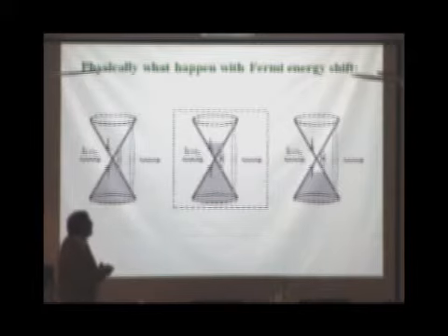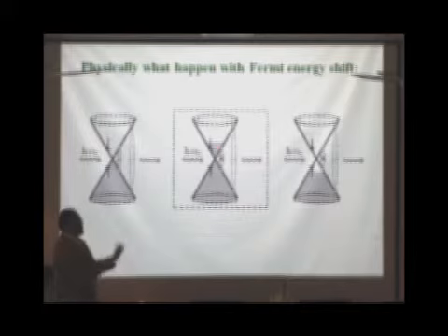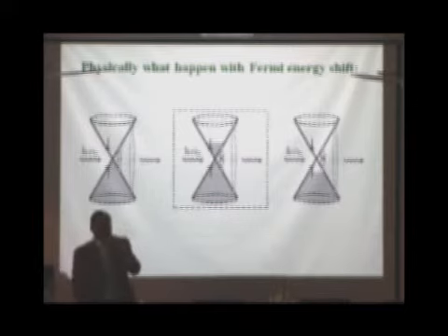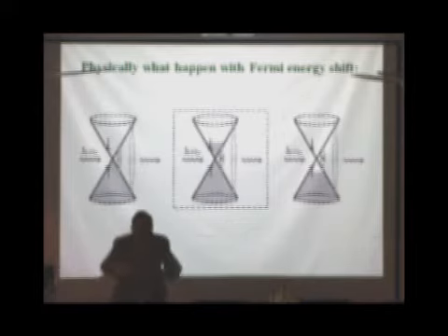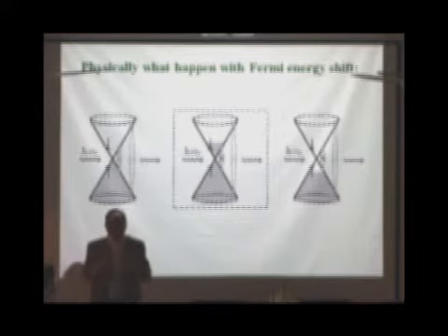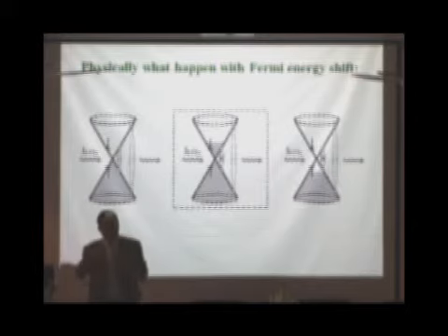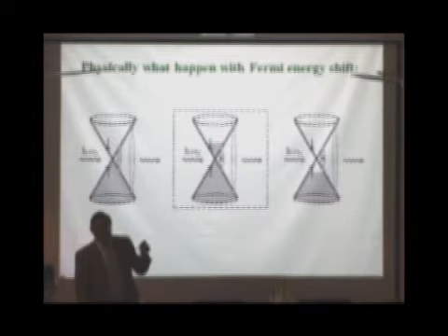Now, what happens when they start doping? These transitions will be forbidden because there is no state available. So the simple physical picture tells you that when you put in doping, when you put electrons or holes, some of the phonon assisted transitions will be blocked. This blocking changes the dressing up of a phonon. It has to readjust, and because of that, the frequency changes, lifetime changes. So this is analyzed in the